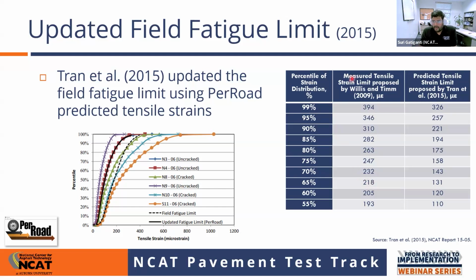Six years later, Dr. Tran and his team took those sections and looked at the difference between the actual field measured strain values and PerRoad predicted strain values, which is an elastic layer theory software. They saw that the measured strain values are always higher than the values predicted using theoretical mechanistic calculations. So if you see the plot here, the dotted line was what was originally proposed by Dr. Willis in 2009, but if we were using the calculated strain values, this criteria was not helping us demarcate sections that failed with bottom-up fatigue cracking from sections that did not. So what Dr. Tran and his team did in 2015 was come up with an updated strain criteria.